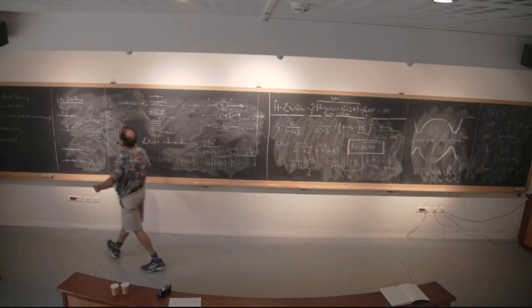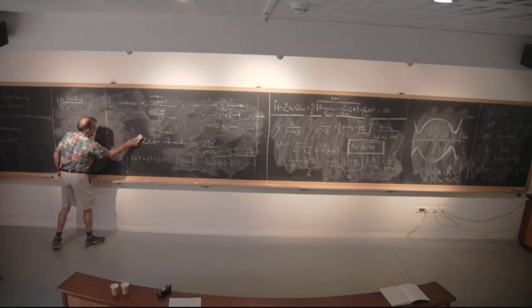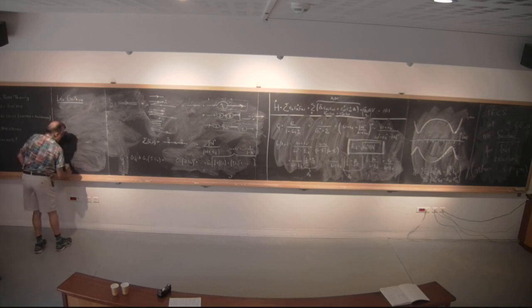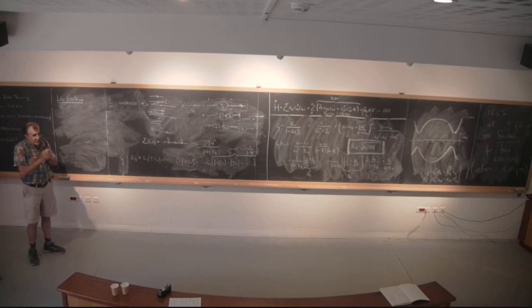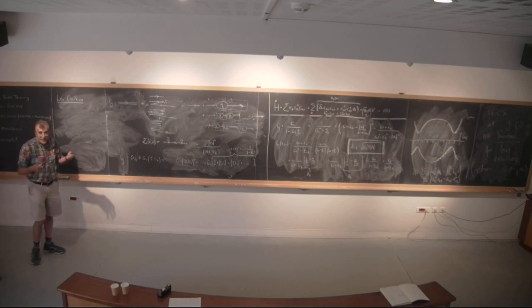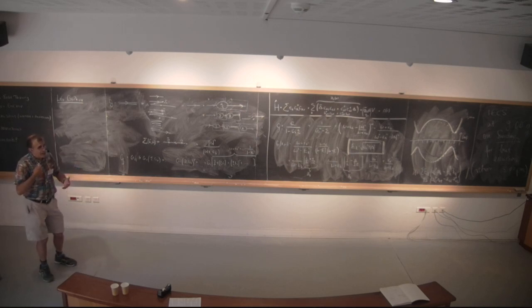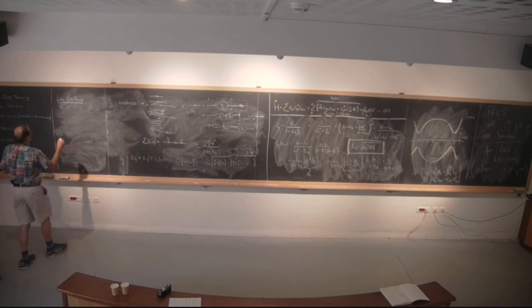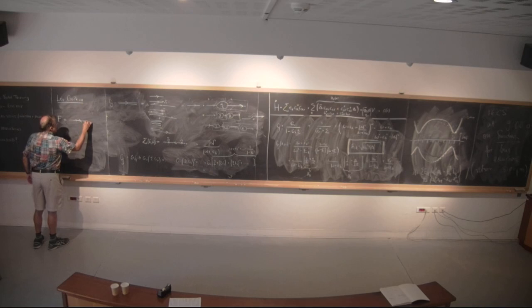And the Andreev component of the scattering is a little bit weird. And he said, well, look, I don't know what this is, but let me give it a name. Let me call it F. It's the anomalous part of the Green's function. If I add an electron initially, and I take out a hole later, well, normally the amplitude for that is zero in a Fermi liquid, because an electron can't convert to a hole. But inside a superconductor, an electron can give up its charge to the condensate and come back as a hole. It can Andreev scatter off the condensate, and that process is called F, and it involves an electron coming along and now scattering into a hole.